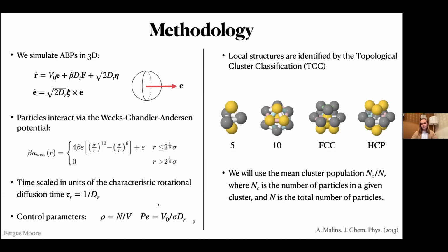For structure, we'll be using the topological cluster classification, or TCC, which is a cluster-based structure which looks at a central particle and then around from that, it compares and fits into known clusters. So we have the FCC and HCP, of course. I'm also including the 5 and 10 particle clusters, which are very prominent in fluids. So it gives us the anti-crystal structures, if you like, which is a good reference point. And then we can look at the fraction of particles in these clusters as a proportion of the whole system as a way to describe what's happening.